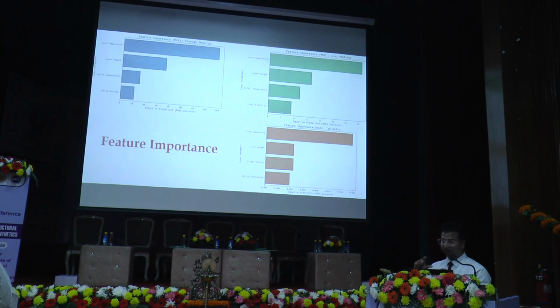So I got this from the machine learning. I got to know which parameter is affecting my property and by how much. The most important parameter was test temperature, because it is a testing parameter, so it gives the highest value in all 3 cases. But among the input parameters, which were layer height, infill temperature, and infill density, for storage modulus you can see the order is layer height, infill temperature, and infill density. A similar pattern in loss modulus, but in tan delta you can see layer height and infill density are upper, and then infill temperature is low. So you can see which parameter is affecting your property and in what manner. This was the beauty of the machine learning models.